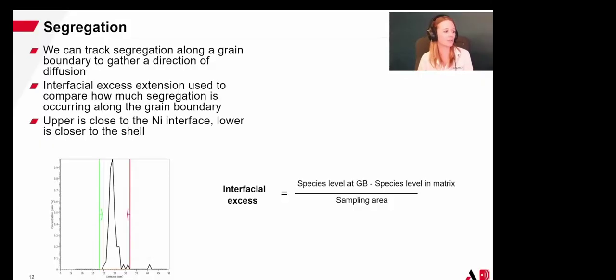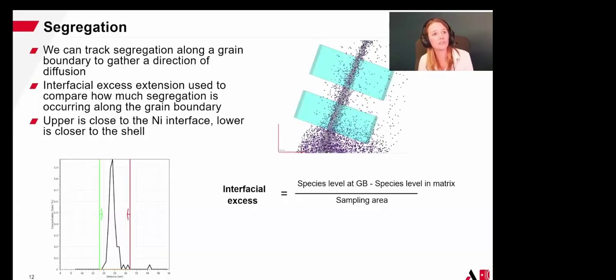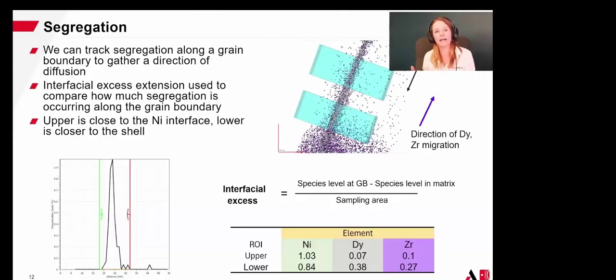Now, the cool thing is that one of our extensions in AP Suite can do this automatically. This is the Gibbs Interfacial Excess extension in AP Suite, and that's going to allow us to quickly and easily do this calculation for a number of different species that may be segregating. So we've done this here closer to the electrode. I've kind of cropped that out of this particular image, but at the top of the screen, that's where that nickel electrode is since we prepared this sample in cross-section. And the second ROI here, region of interest, is closer down into the bulk of the material, and this is just above one of these shell regions, so we've kind of excluded that from the analysis. But one of the things that we can do is look at how different species might be segregating at the top close to the electrode and lower down in the ceramic matrix.